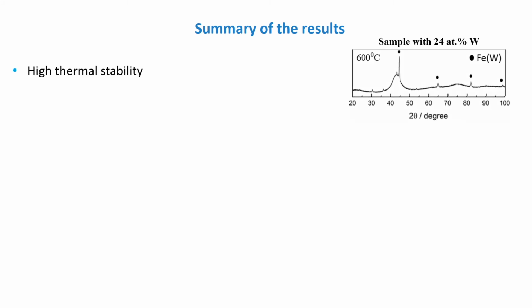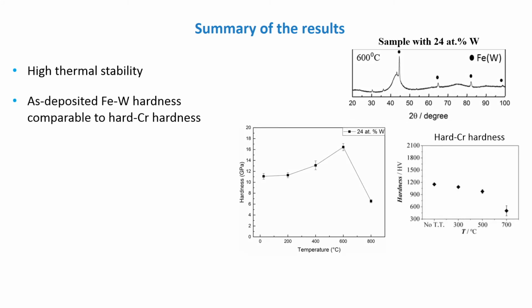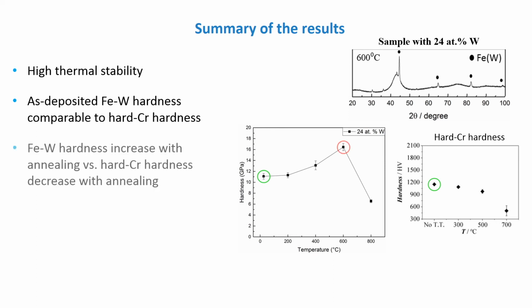As a summary of the results of the work done, we saw how the iron tungsten coating rich in tungsten is characterized by a high thermal stability and by an as-deposited hardness comparable with the hardness of hard chromium, and its hardness can be further increased upon annealing up to a maximum value of 16.5 gigapascal. The results obtained are promising. What will follow now will be to study the corrosion properties of the iron tungsten coatings.